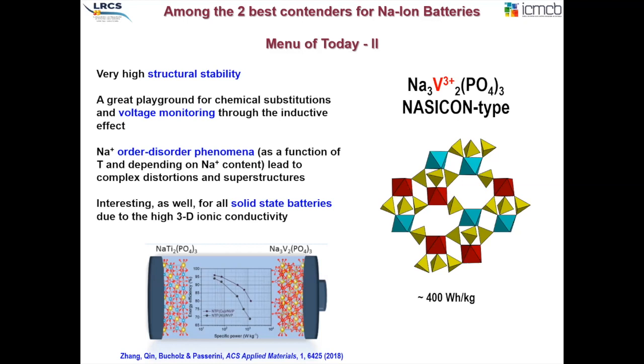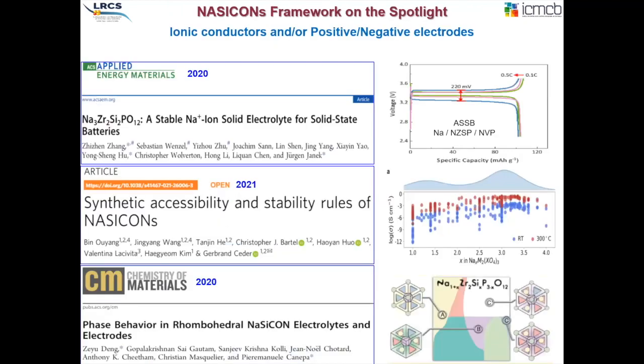We can play with many chemical substitutions into this framework, so that really allows the voltage monitoring through the inductive effect, as many people know. And this is also quite fascinating in terms of crystal chemistry, where we observe many order-disorder phenomena on the sodium sublattice. Not to mention as well that several of these materials have been tested or are studied for sodium solid-state batteries, both for the cathode or anode part, but also using Nasicon as the solid electrolyte in between.